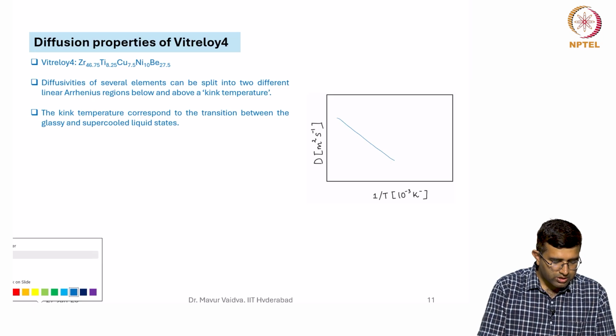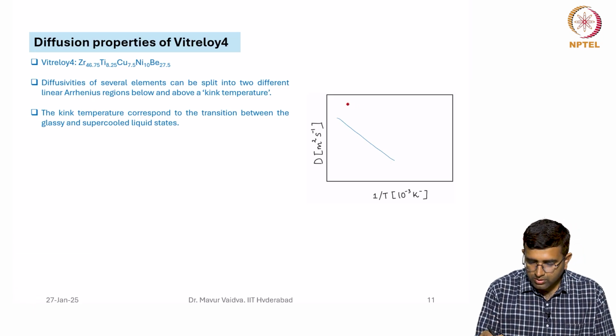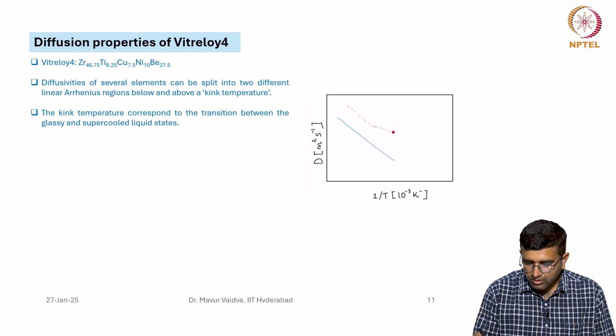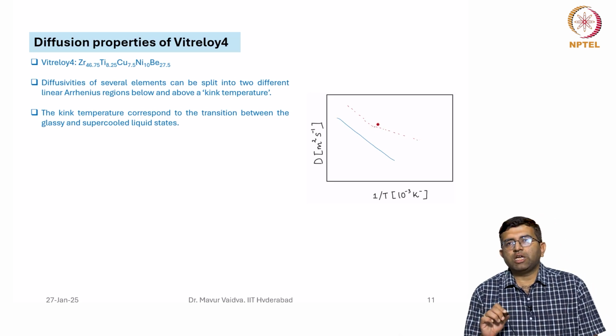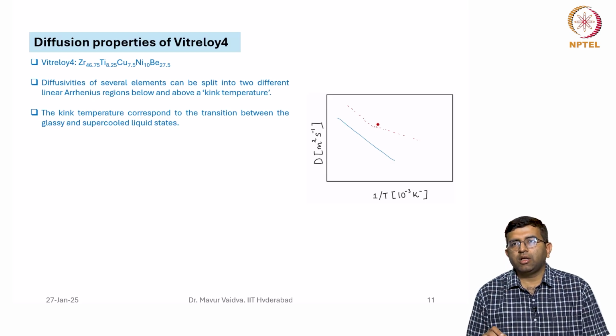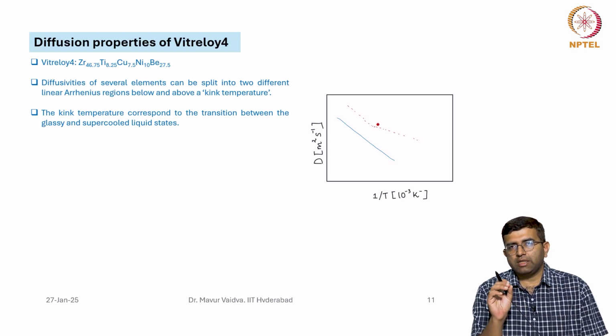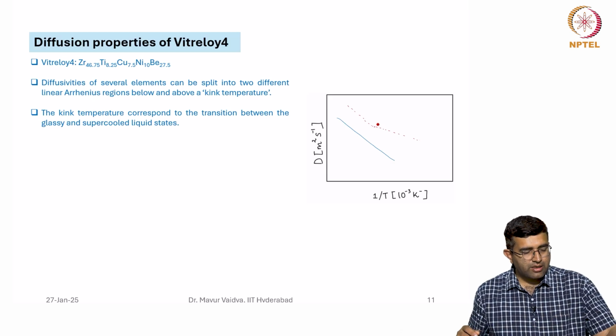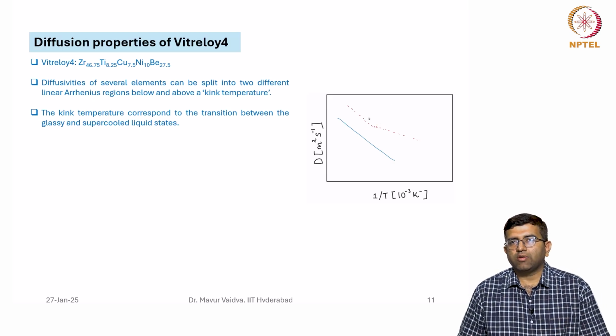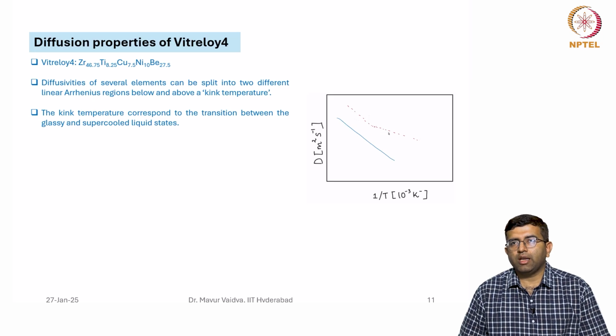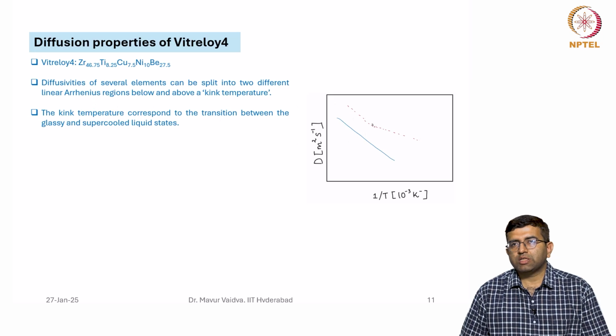So I will just show it in a different color, that is to say a small change in the slope. I have exaggerated this a little bit. In the actual data, you will see that the change is a little less. But the point to take away is that there is a change in slope in the Arrhenius line. So it is represented by two different linear Arrhenius regions. This temperature is known as the kink temperature.